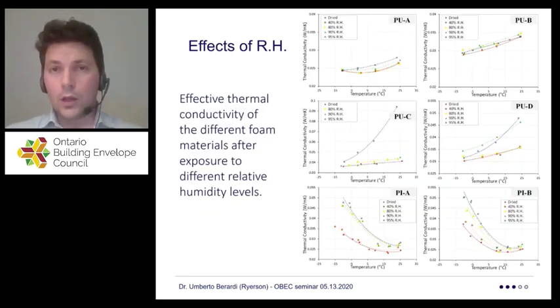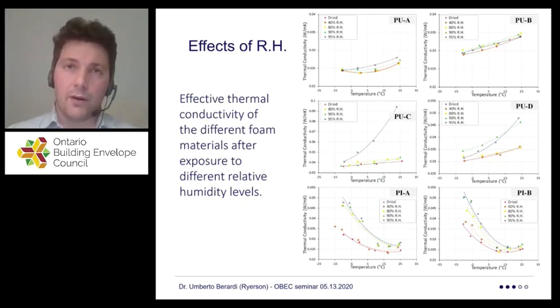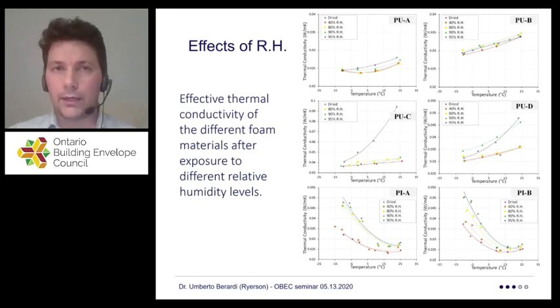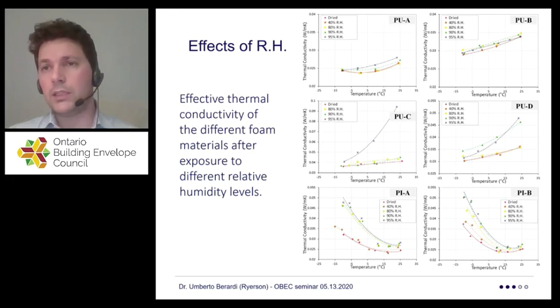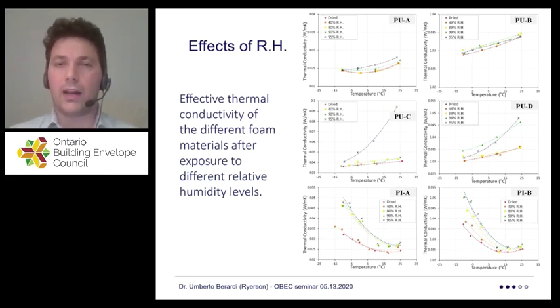So we did the same kind of experiment I was telling you before, testing a lot of different foams, polyurethane, polyisocyanurate for different kinds of relative humidity levels. We brought in a climate chamber, left the material for months, tested after a month of exposure at that relative humidity.